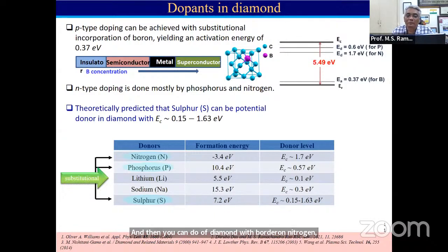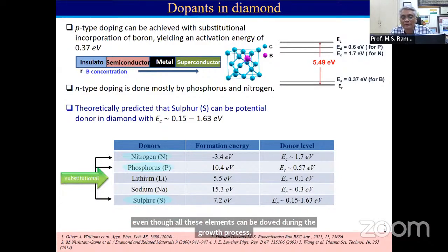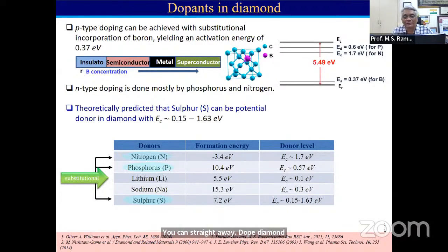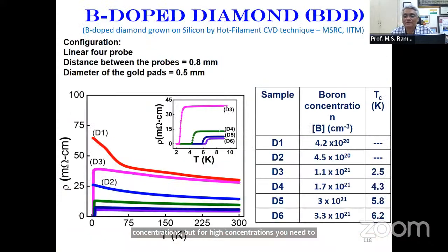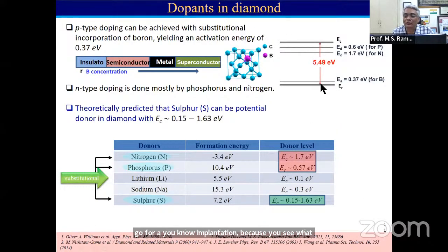Well, anything beyond boron is always challenging, even though all these elements can be doped. During the growth process, you can straight away dope diamond with boron easily. Nitrogen and phosphorus can be doped at lower concentrations, but for high concentrations, you need to go for implantation.